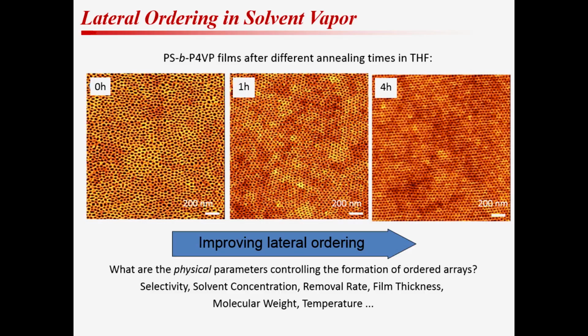I take this film and I put it in a solvent. It happens to be tetrahydrofuran. It's just a solvent that's a good solvent for polystyrene and a good solvent for polyvinylpyridine. And I just put it in the vapor. And in this particular case, I left it for an hour or 4 hours, but you can make this go much more rapidly. And what you find happening is that these little cylindrical domains start to get much better defined,